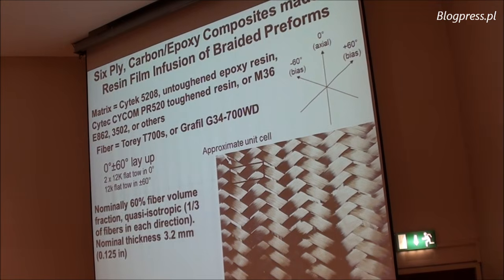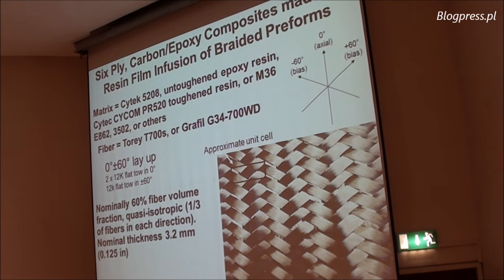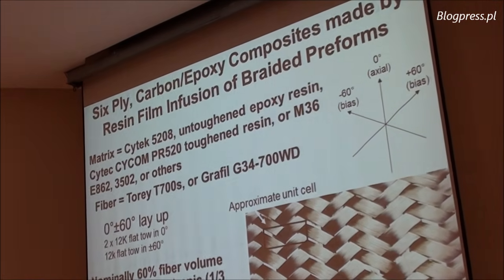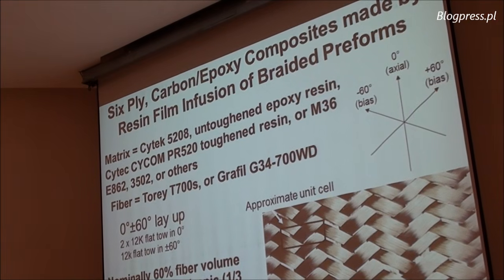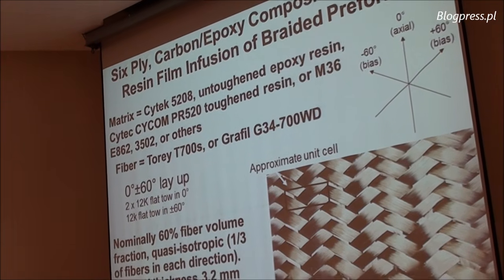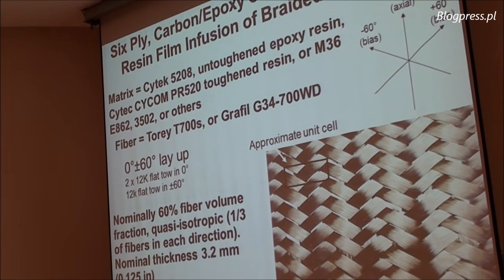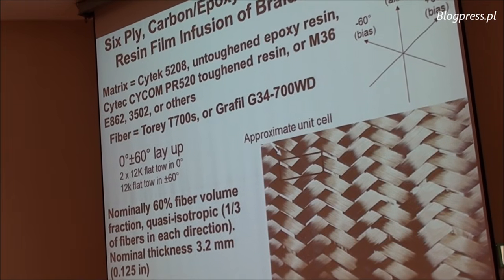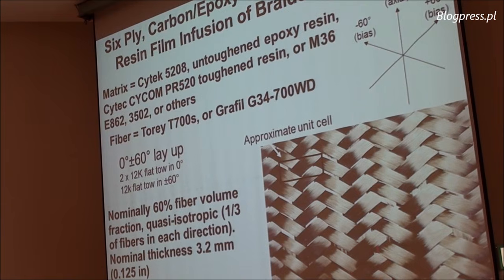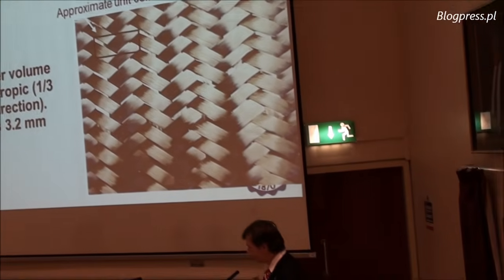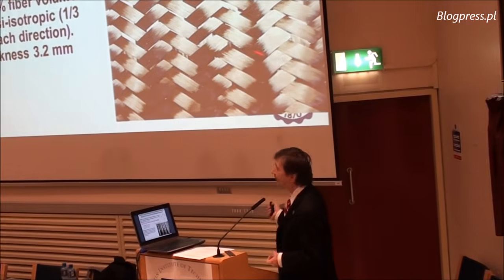We use different matrix materials and limited ourselves to Toray T700S fiber, which is Japanese fiber. And you can see architecture, and again, the same architecture is seen here in the sample, which has 3 directions of the fiber. 0 is embedded inside of these bundles, and plus minus 60 braided over and under through the system of braiding. So this, in mechanics of composite, we call it quasi-isotropic material. It means that from the point of view of theory, it's supposed to have the same properties in axial direction, which is this one, as in transverse direction.